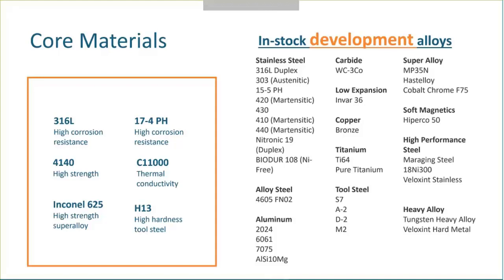Another question on the part. So if you were to print a cup, let's say, would that cup be watertight, or if you were to do a channel in the part, would that hold pressure at all? Is there any porosity that would not be airtight in these parts when they come off the sintering furnace? So I don't want to say there's no porosity, there's some micro porosity because we are around that 98% density range, but they are watertight parts because it goes through that shrinkage and that sintering process. We don't have those large voids like normal FDM plastic parts have. We do actually have watertight surfaces.